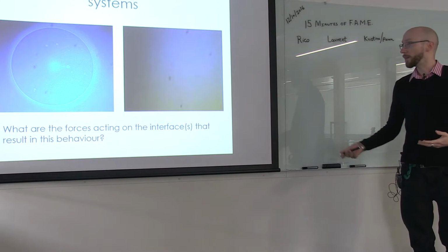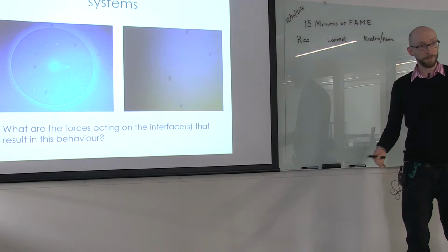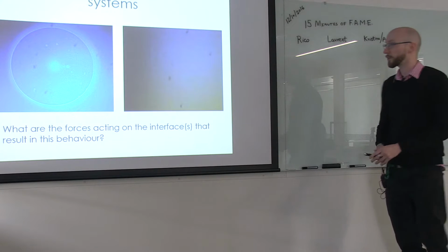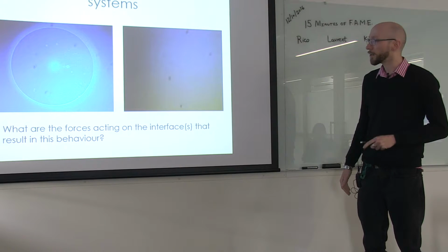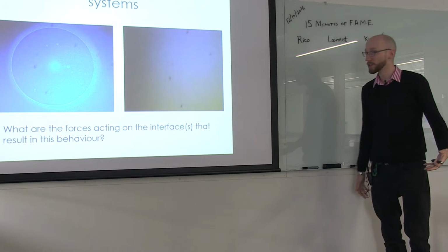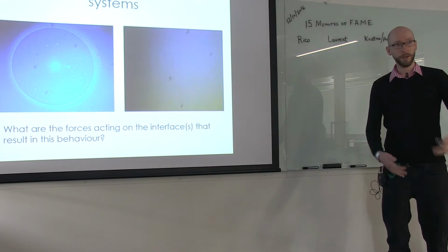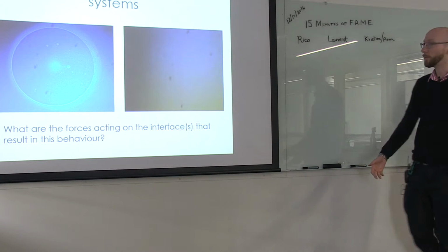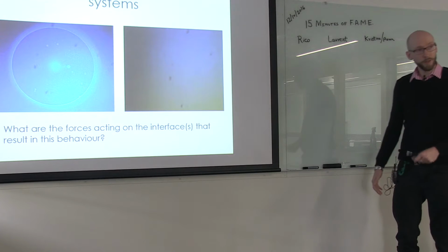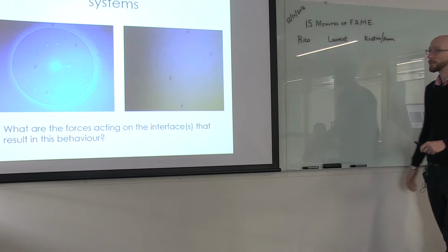Well, we have a complex set of forces. We've got surface forces, so we've got things like the charge in the system, so the bubble interface and the glass interface below it are going to be charged. We've got the van der Waals interaction, ubiquitous electrodynamic interaction that exists between all matter. And we've also got hydrodynamic interaction in this instance.